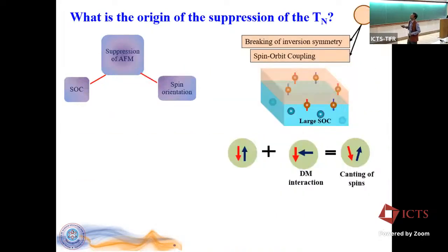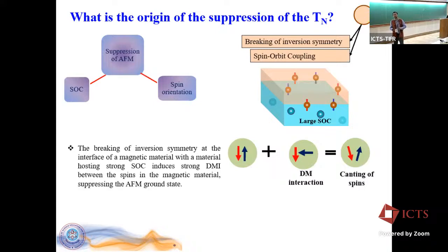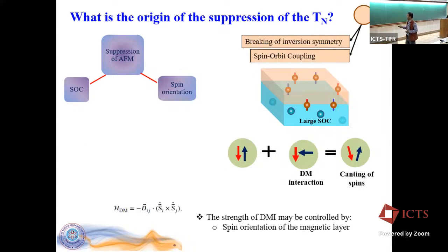Now the other two possibilities, as I was just pointing out, are the SOC and the spin orientation. To remind you, for MnPS3 and FePS3 the spins are out of plane, it's vertical, and for NiPS3 the spins are in plane. So what we think is the underlayer has a large spin-orbit coupling, and that introduces DM interaction in the spin interactions in the magnetic layer, and therefore there is a canting in the spins, and that eventually loses its magnetic ordering, which is what we proposed, and that also helped us with the understanding of the spin orientations.